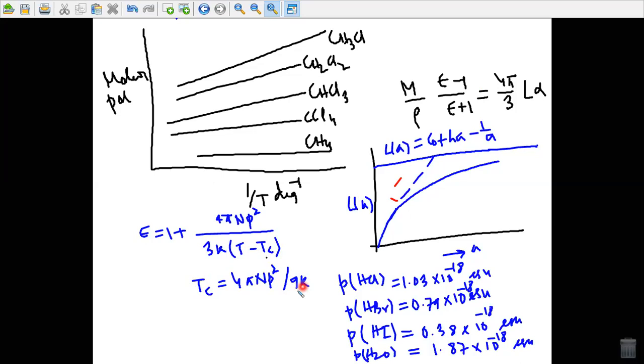The dielectric constant would really become infinite at t equals Tc, right? So this becomes infinite at t equals Tc. But rather than that, the saturation effects should enter and the substance should become spontaneously polarized, or ferroelectric. Actually, ferroelectric behavior is at present unknown in dipolar substances, although it is found in crystals which are more or less ionic in binding. We will discuss ferroelectric and piezoelectric crystals later on.